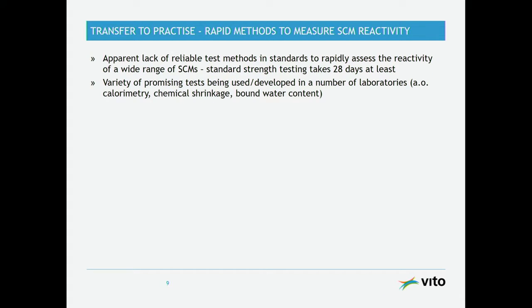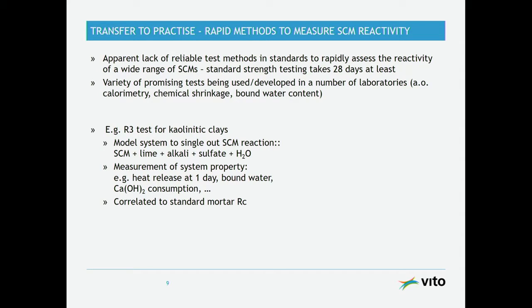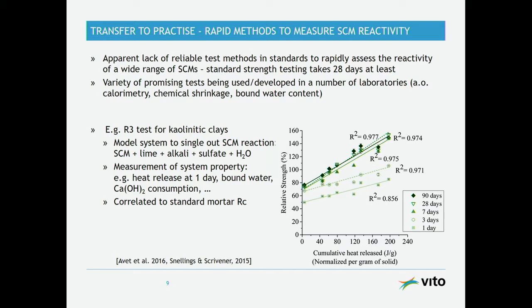So if we want to go to more reliable test methods that can also be applicable in the field or at cement plants or for quality control, then we would need some simpler methods that are also as reliable in, for instance, predicting the compressive strength development. For this purpose, there are already quite a few promising test methods around, and we also did some work at EPFL, this work for kaolinitic clays, in which we measured the heat flow as a function of time and compared it to the relative strength of mortar bars. And we see that if we mix the metakaolin or the kaolinitic clays in a system with lime, alkali, sulfate, and water, the heat flow that is coming out, or even other properties like bound water or portlandite content, can be related to the standard mortar relative compressive strength.